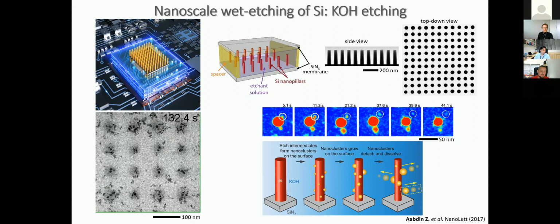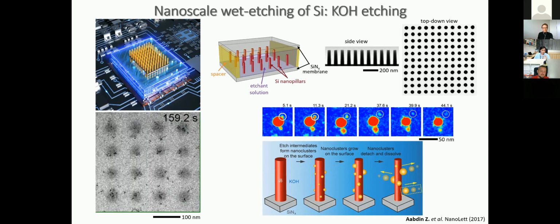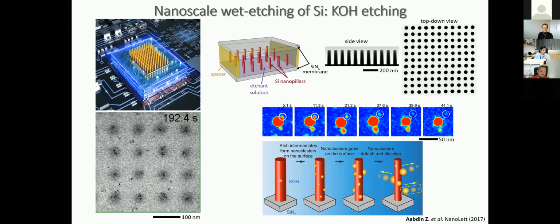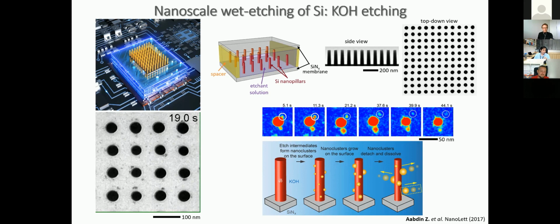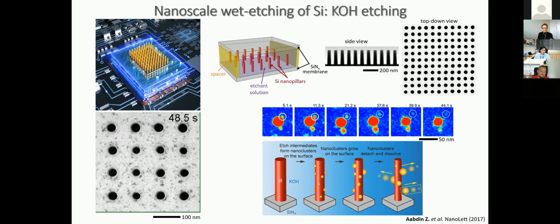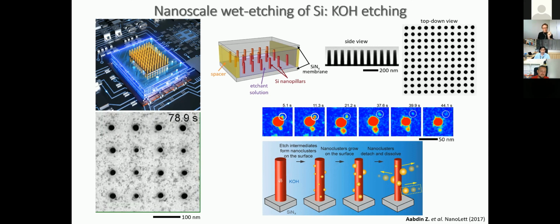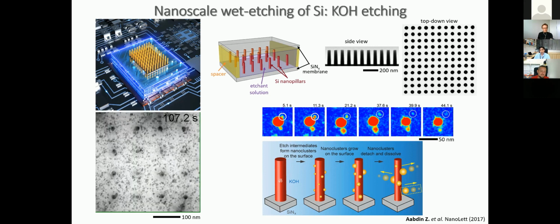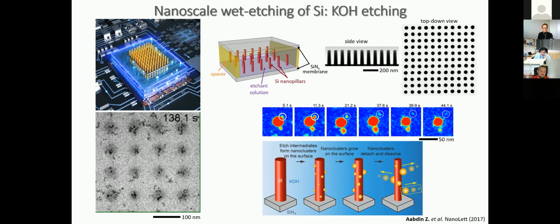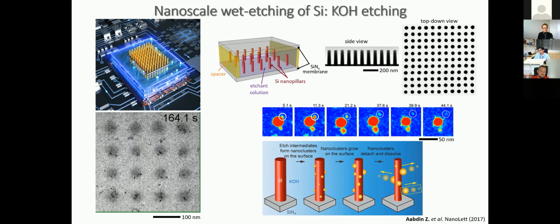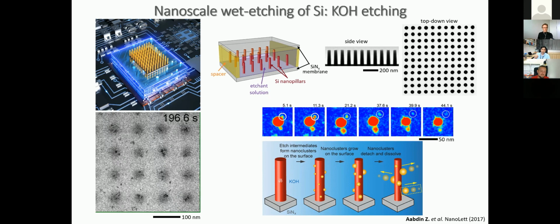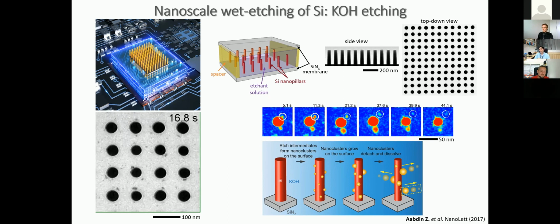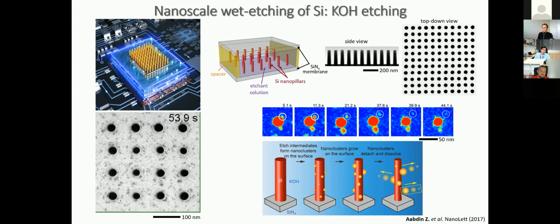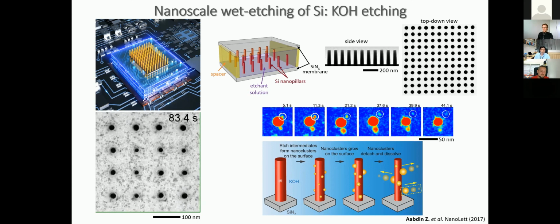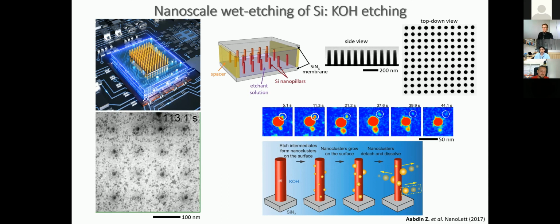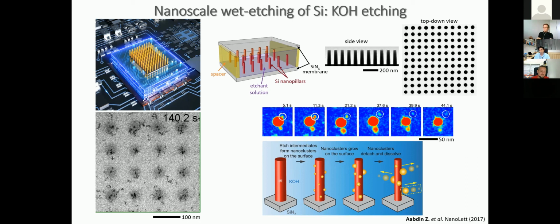And what you see here during the etching is you start with these nanowires, and as it slowly etches, the reaction product starts appearing, right? So what is happening here? Reaction products appear, nucleate on the surface, detach, and dissolve in the solution. But if you look at the classical textbook description, open any microfabrication textbook, it's a reactant coming, reacting with the surface, and then the byproduct detaching and moving into the solution. But that's not the case. All the byproducts sit on the surface, and then they nucleate, and only when they reach a certain critical size, they detach and then start dissolving in the solution.